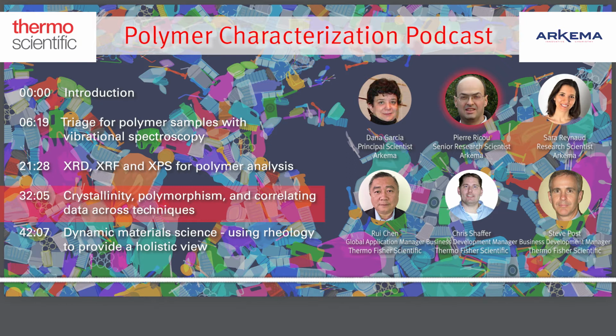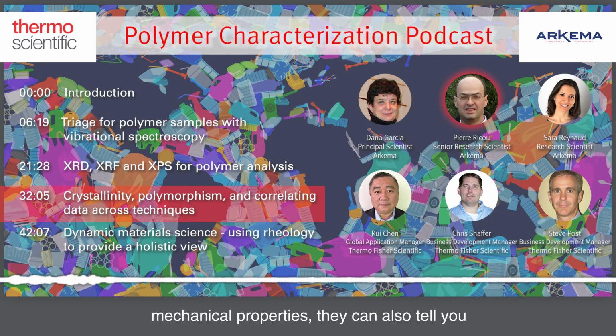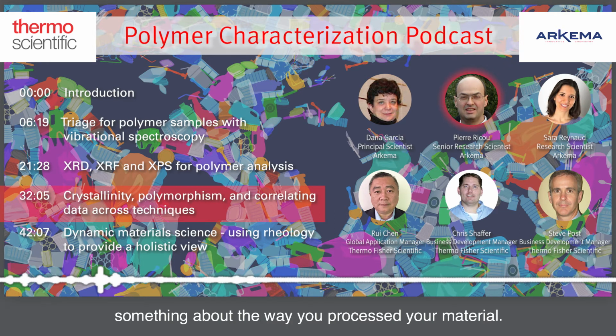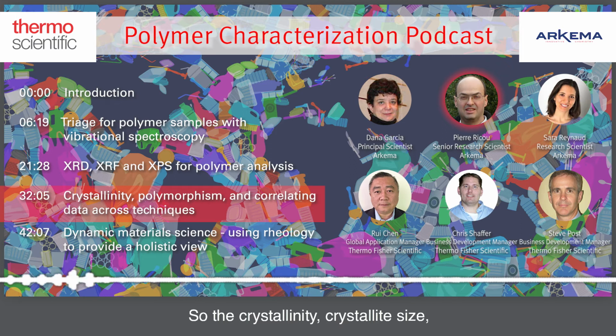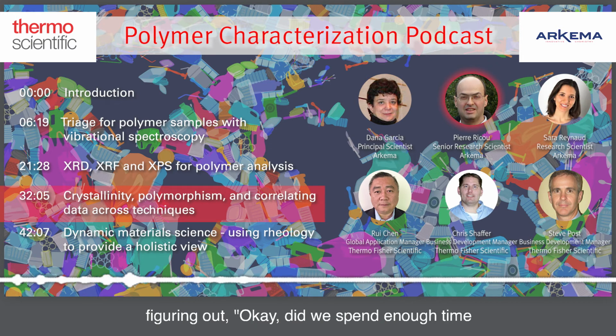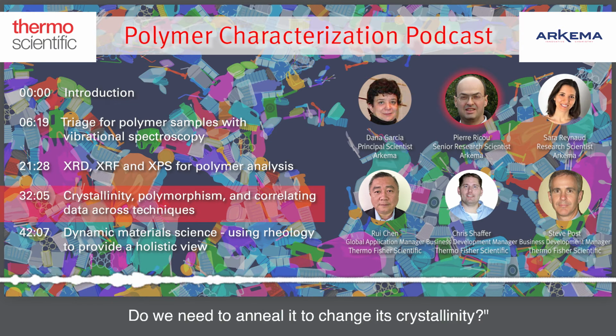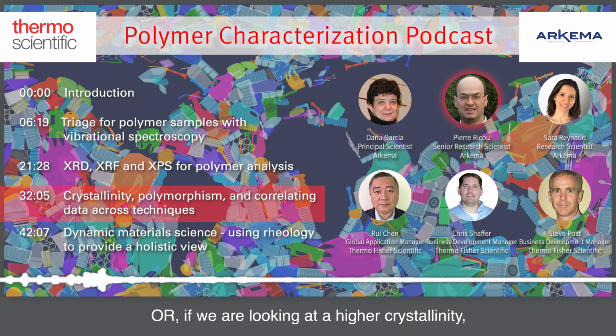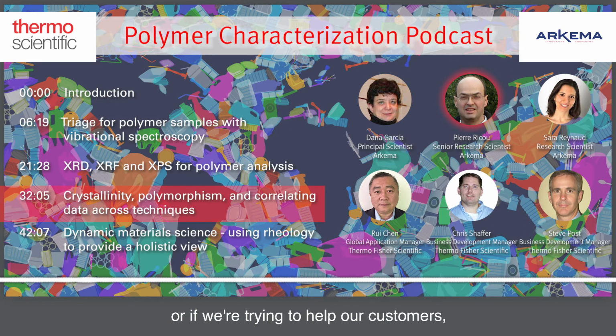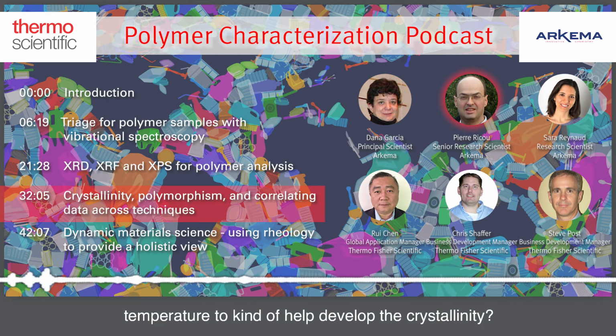Beyond the fact that they impact mechanical properties, they can also tell you something about the way you processed your material. With the crystallinity, crystallite size, and lamellar thickness, you start figuring out: did we spend enough time when molding that part? Do we need to anneal to change this crystallinity? If we are looking at a high crystallinity, did something change in the process? Or if we're trying to support our customers, can we tell them that they should probably operate at a slightly higher temperature to help develop the crystallinity?